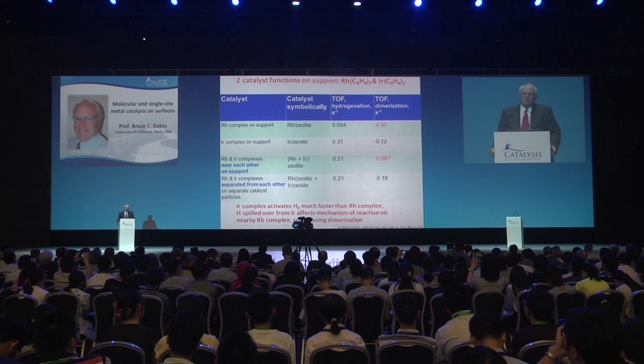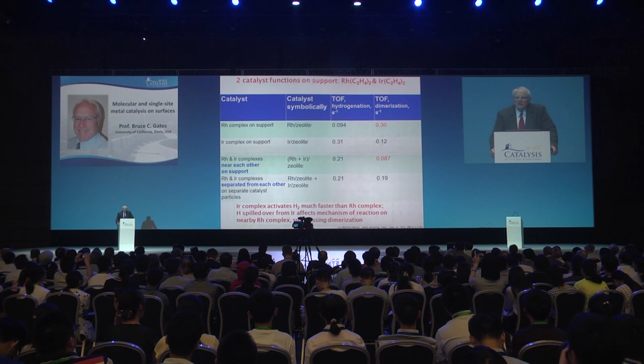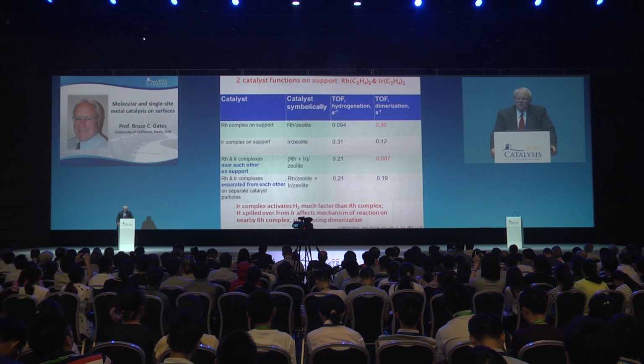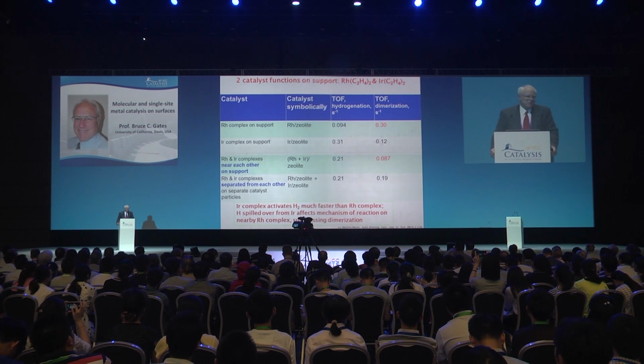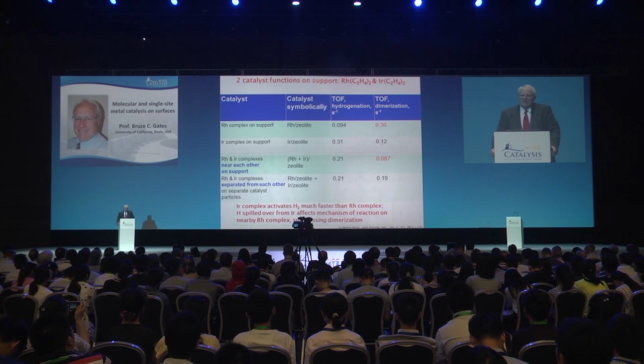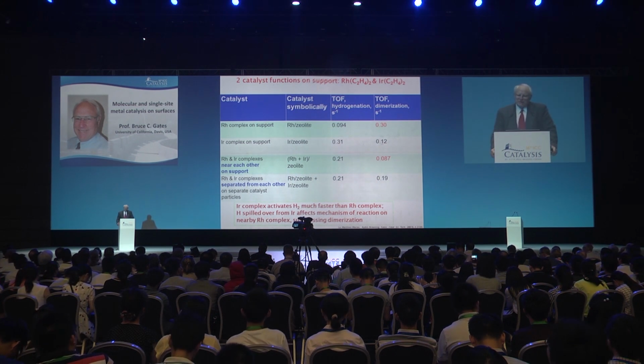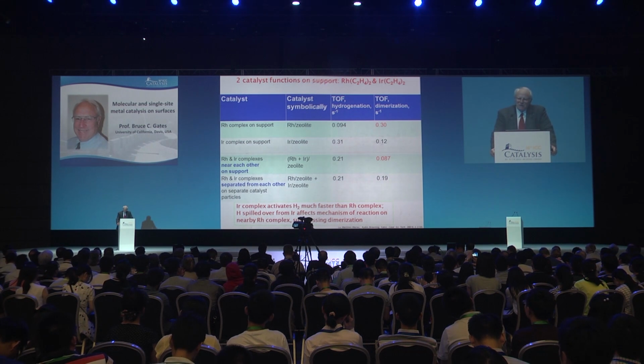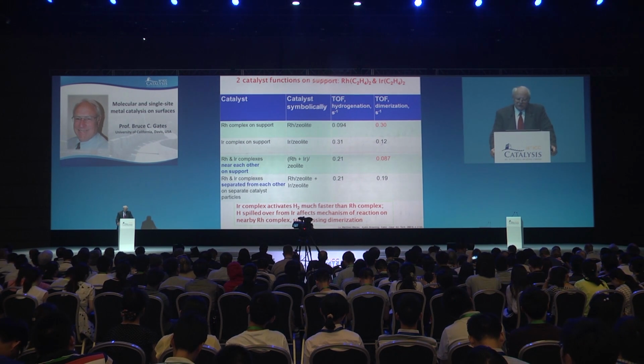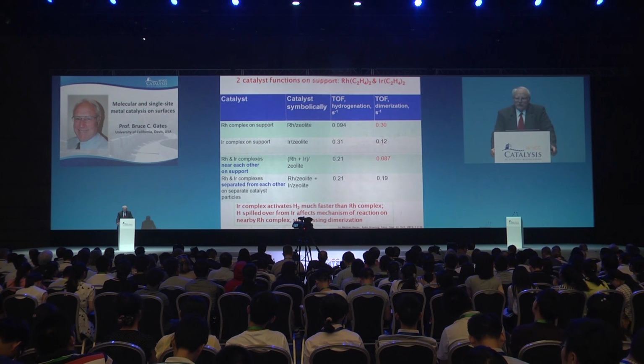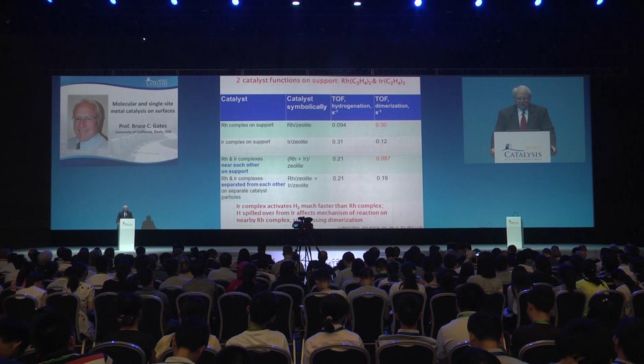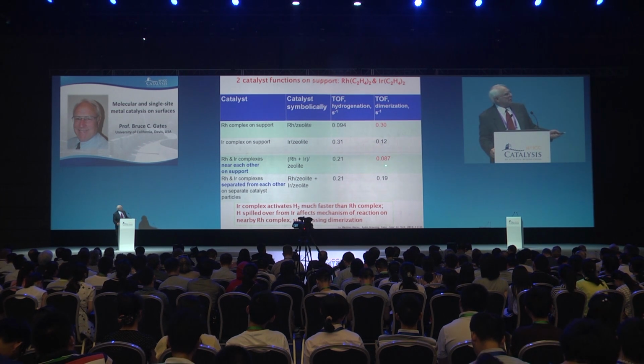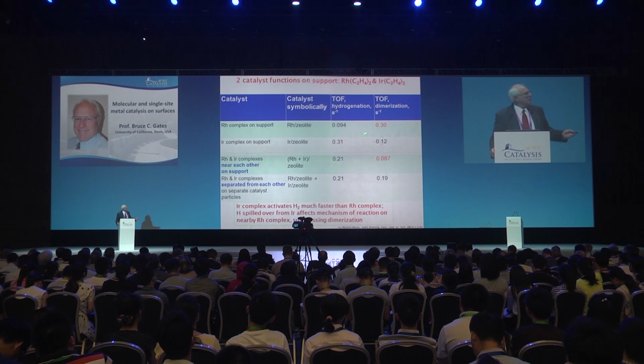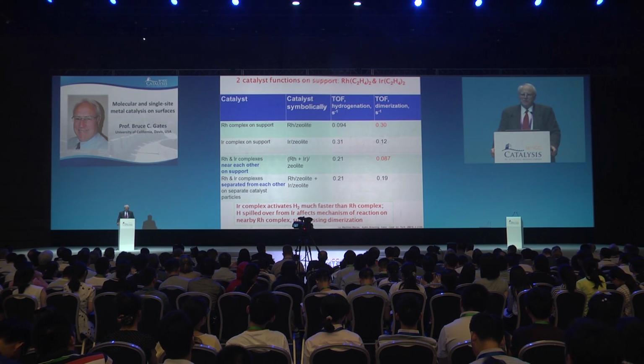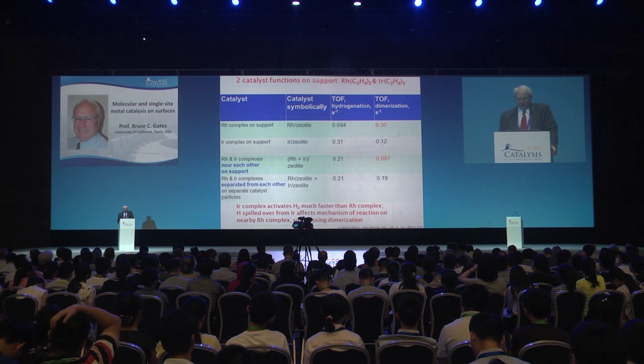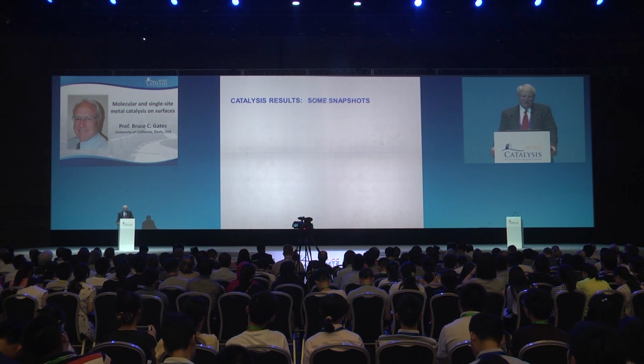But if the two metal centers are near each other, there's a dramatic effect of one on the performance of the other. I don't have time to explain this well, but it's about activation of the hydrogen, which the iridium does much more rapidly than the rhodium, and then spillover of that hydrogen, which somehow affects the structure of the catalytic species responsible for dimerization. So when we put those two metal complexes near each other on the support, we dramatically decrease the selectivity for dimerization. That's the final design variable we're going to talk about.